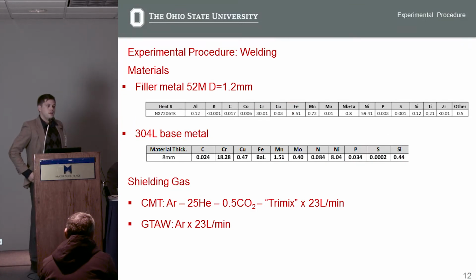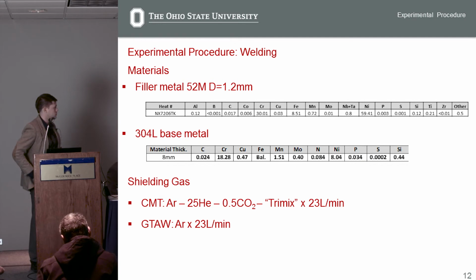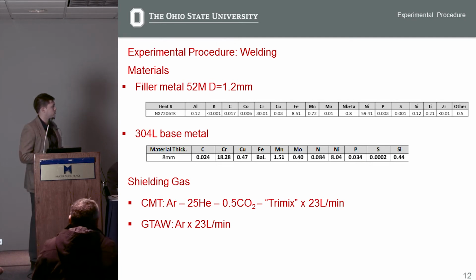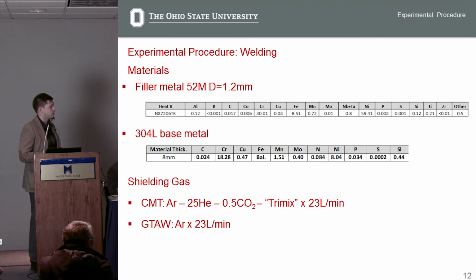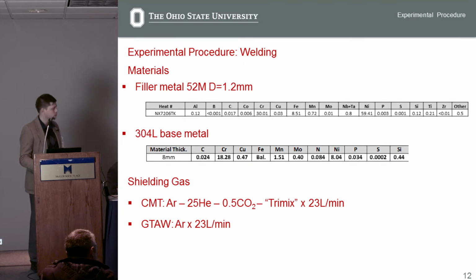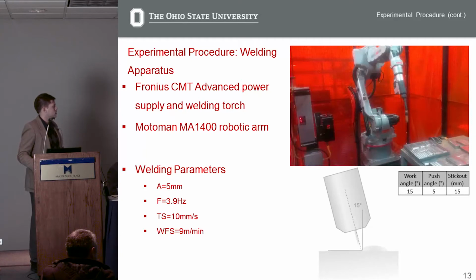So after we did the DOE and after we did some EDS on weld samples, it was time to make a mock-up weld. We chose this particular heat of 52M with this composition, and we overlaid it on 8mm thick 304L base metal as a mock-up overlay, and we used this shielding gas, which was a combination of argon, helium, and CO2. The welding apparatus was the Fronius CMT advanced welding power supply hooked up to a 6-axis Motoman robotic arm. The welding parameters were very similar to the optimized ones that I discussed previously, except we turned up the wire feed speed to increase our dilution a little bit to assuage some lack of fusion fears.